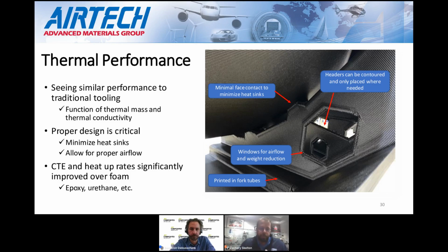In that process, we've seen vastly improved thermal cycles compared to things like epoxy or urethane foams. In general, they fall between a metal tool and a composite tool in their thermal performance. So quite good performance in general, allowing for really good cycle times through the autoclave.